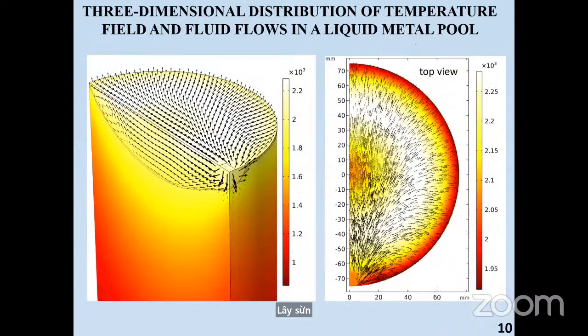The position of the crystallization front on the slide is shown by two isotherms with the temperatures of the liquidus and solidus. The value of the temperature range of the transition during the calculation was assumed equal to 50 kelvins. Next slide.